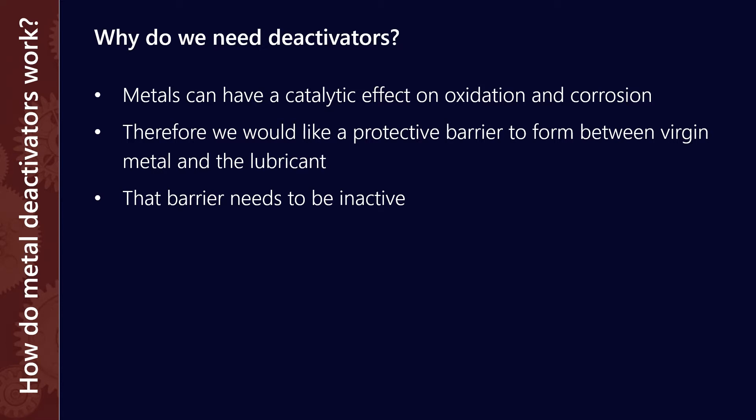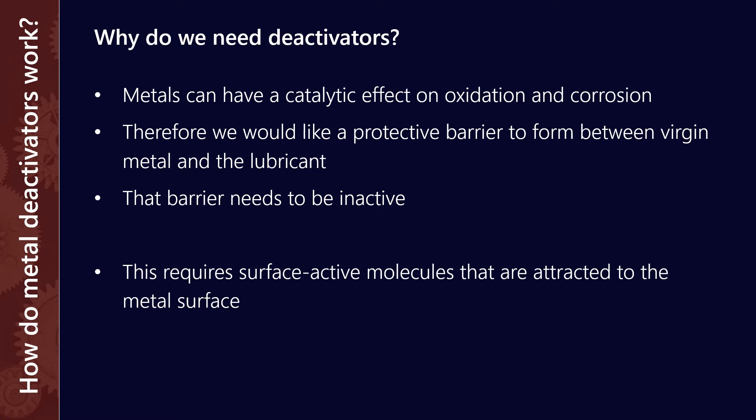The other thing that can happen is that if you get corrosive byproducts, they can increase the acidity of the oil and cause further corrosion. So what we ideally want is some kind of protective barrier to form between virgin metal and the lubricant itself. As that barrier wears away, you want to have sufficient additives within the lubricant so it can reform. That barrier ideally needs to be inert or inactive, so it needs to bind to the metal surface and then not chemically react with anything else.